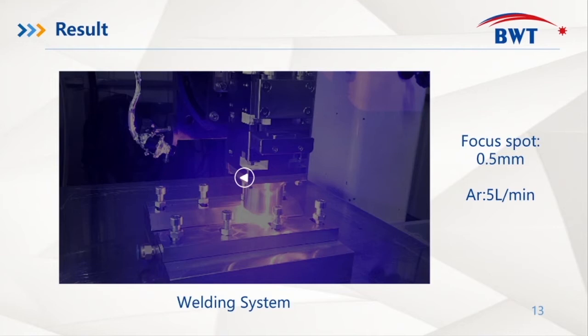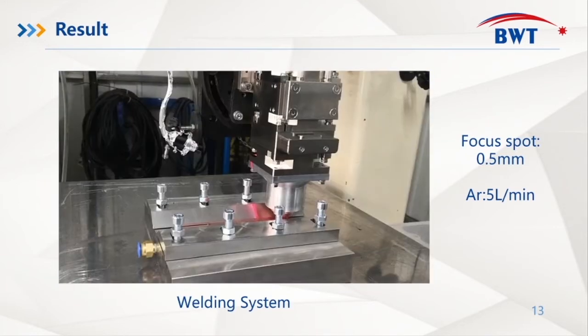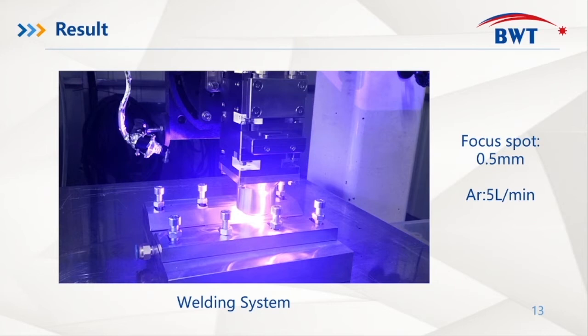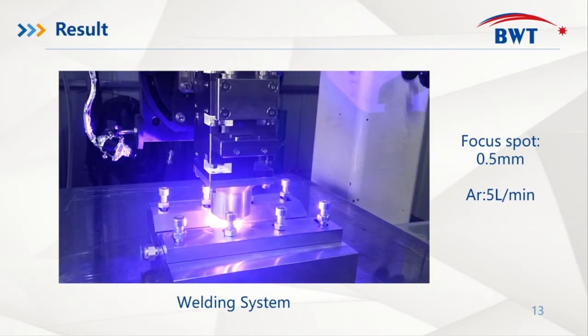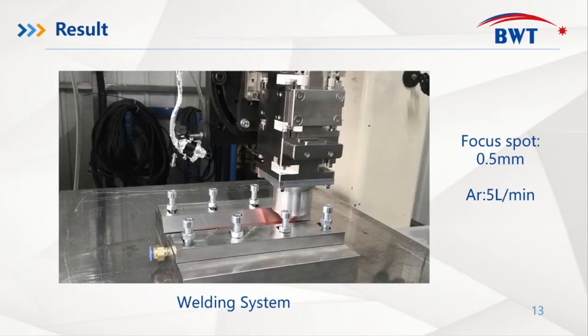Copper, stainless steel, and aluminum samples are welded to test the performance of the system. Collimating lens, focus lens, and protective lens are integrated in the welding system, but all lenses are not spherical aberration eliminated, which will have a negative impact on welding penetration. A spherical aberration eliminated lens group will be used as one of the optimization methods in the future. These lenses have anti-reflection coating that allows a transmission of more than 99% for blue laser. With a magnification of 1.5, the diameter of the focal spot on the workplane is about 0.5 mm.